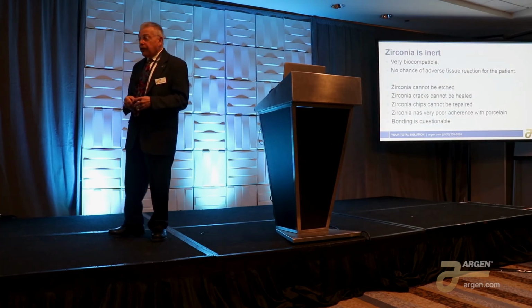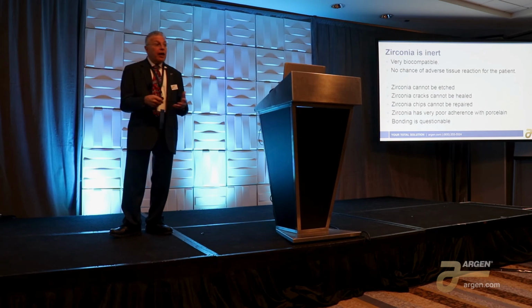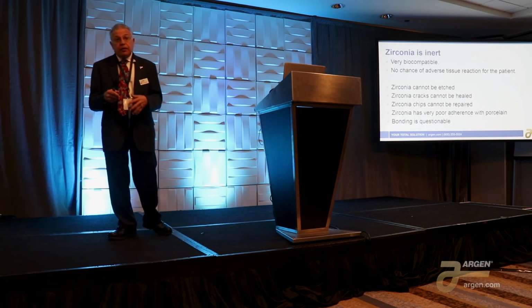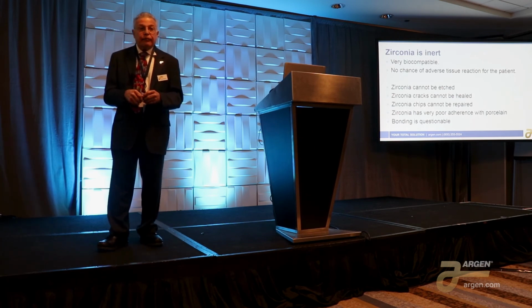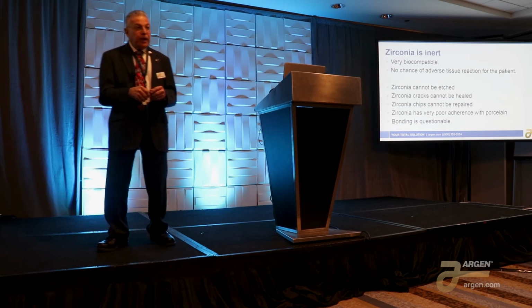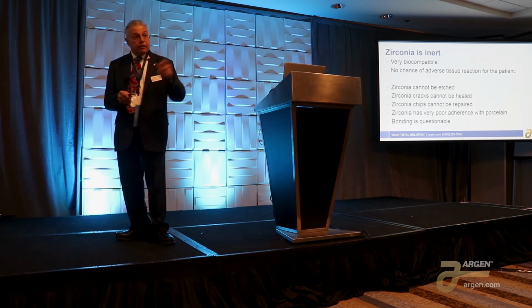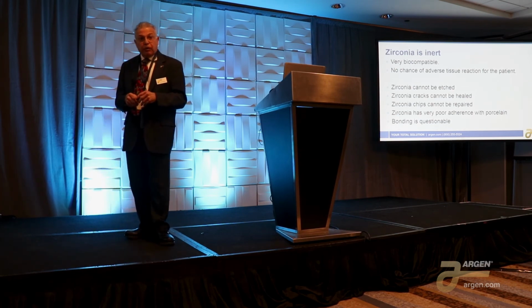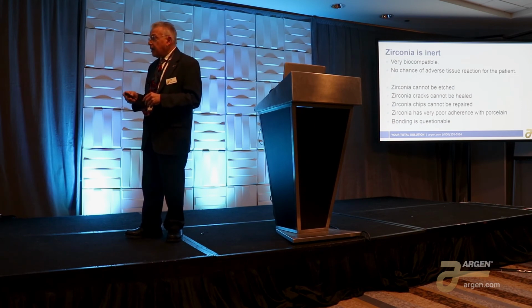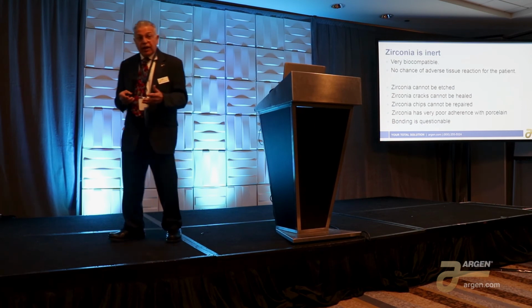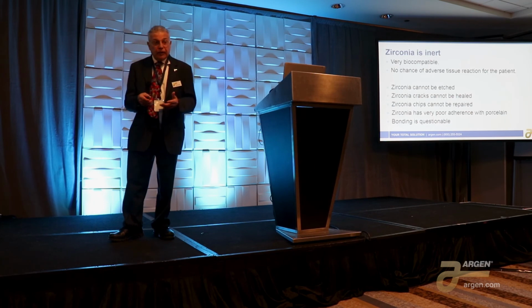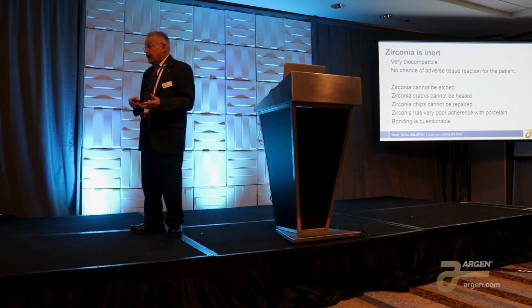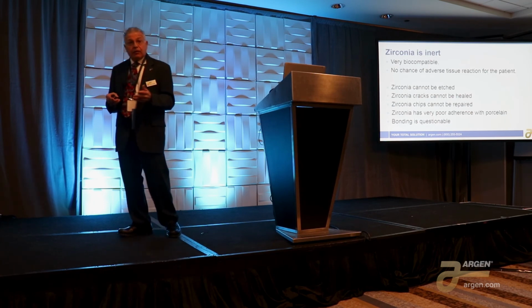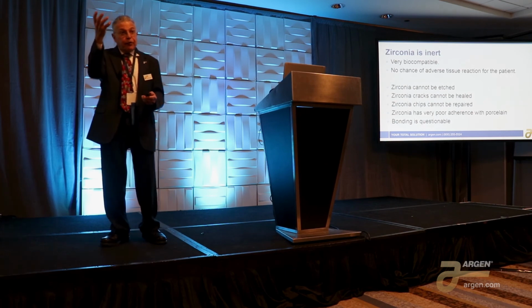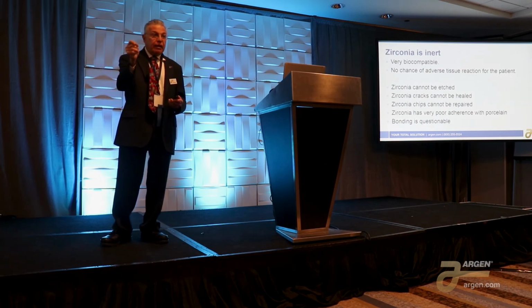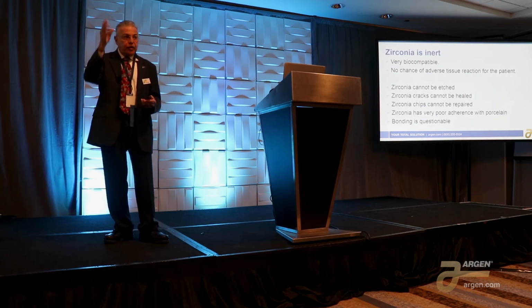Now, zirconia is very inert, which means it's very biocompatible. That's fantastic. There's not going to be any adverse tissue effects to the patient. As a matter of fact, the cements may be more affected than the zirconia. But because it's so inert, it can't be etched like we do dental porcelain. Any cracks can't be healed. You remember when you took a PFM out and you saw a little crack coming out on the pontic, you just put it back in the furnace again.